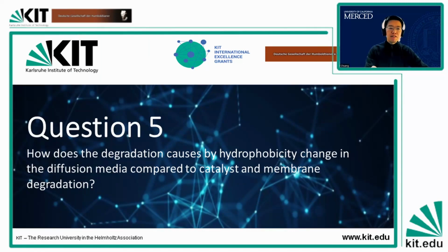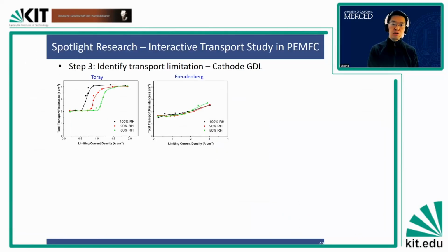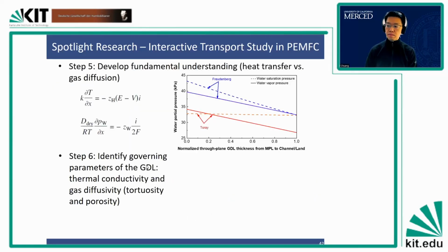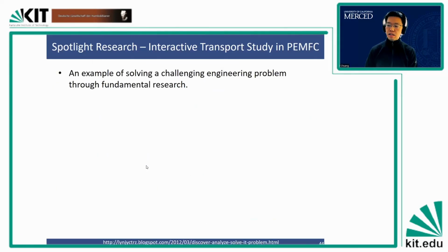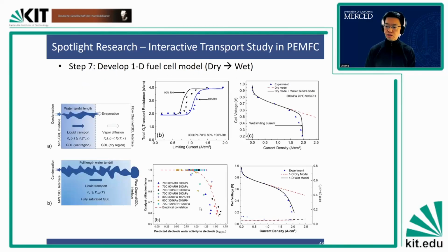And on top of that, what's even more complicated is that there will be local transport resistance in the catalyst layer, which is related to flooding as well, which we actually observed. That was the work that we did on this level of study, where different catalyst utilization is actually responsible for flooding as well, more related to the catalyst layer. And so yes, you are absolutely correct.